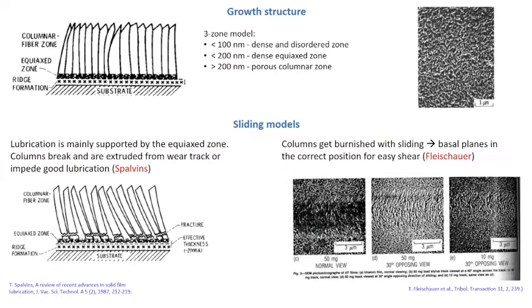Okay, going to the sliding models, in this case we have two most important hypotheses related to the sliding. One is proposed by Spalvins himself, and the other is proposed by Fleischauer. Spalvins states that the lubrication is supported mainly by the equiaxed zone, while the presence of the columns does not really contribute to the sliding, and sometimes they can be also detrimental because they represent abrasive third bodies.